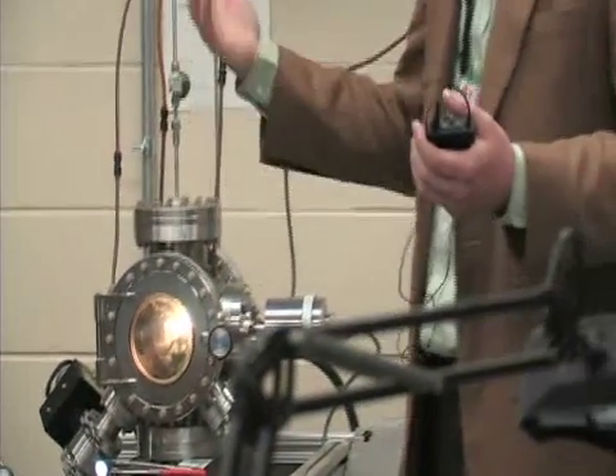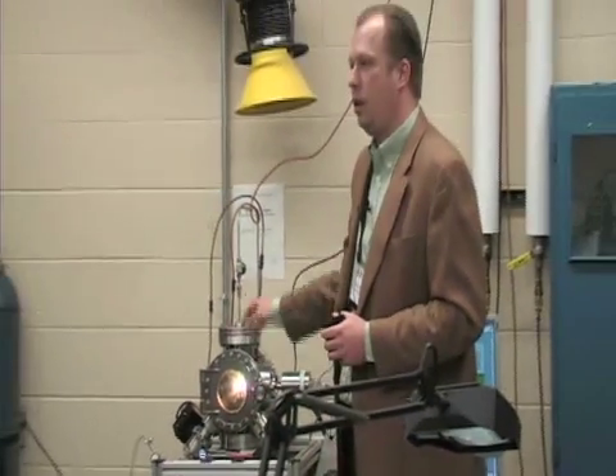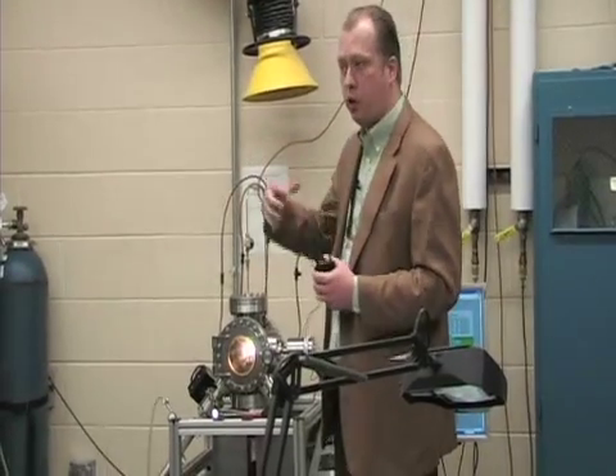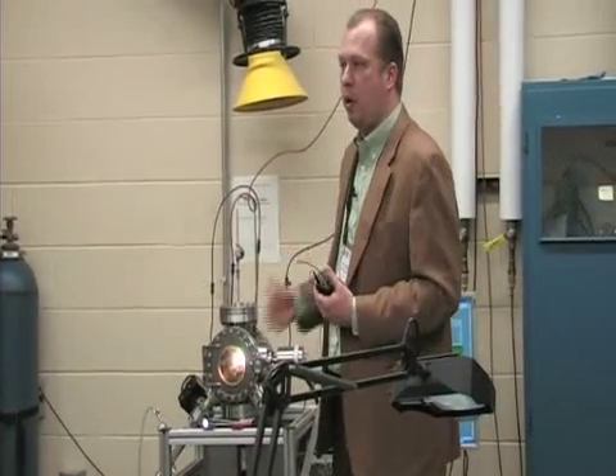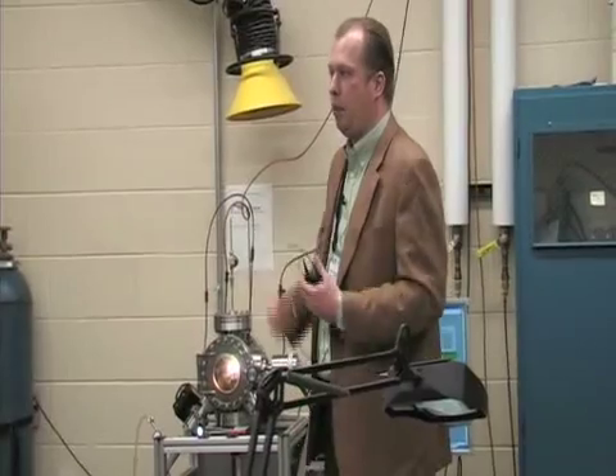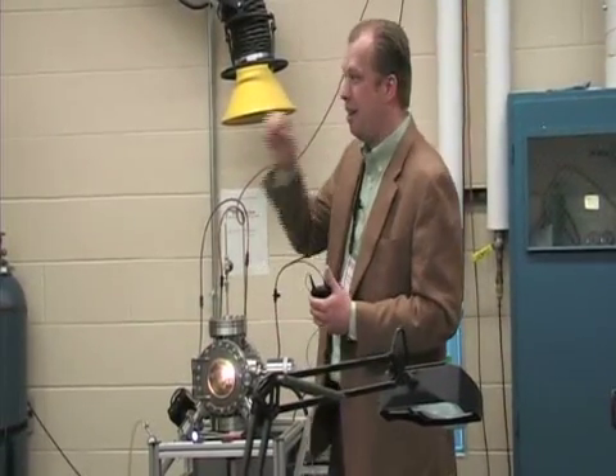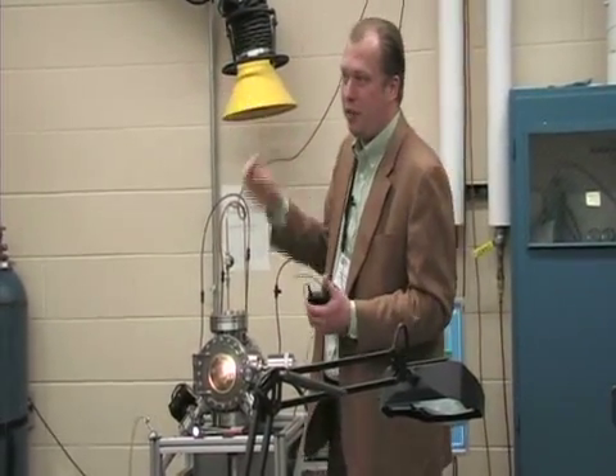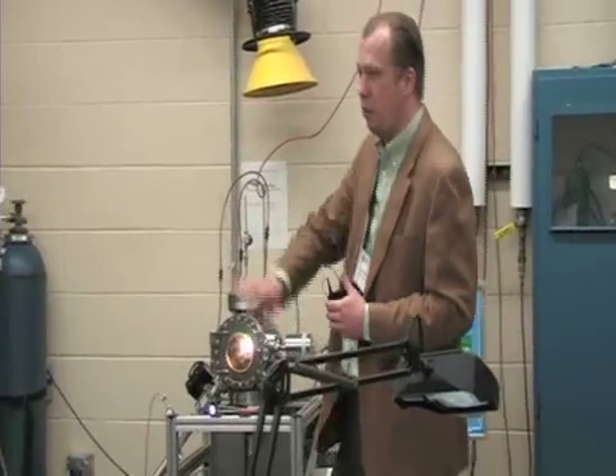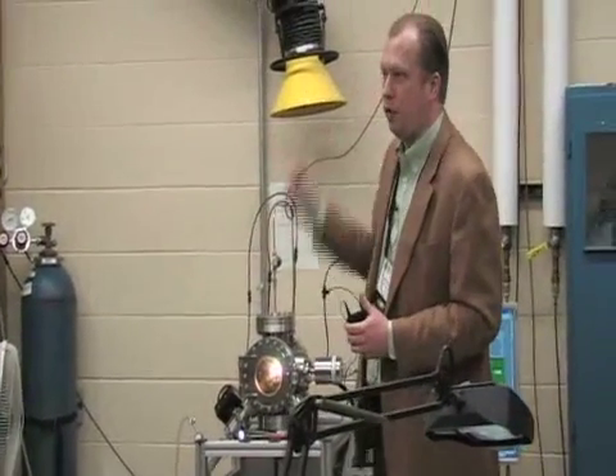Even with something as easily machinable otherwise as aluminum, we can see sometimes significant force reductions when we're micro end milling with the diamond coatings because there's less adhesion. And also, a big thing, the chips don't stick in the flutes. I'm not even just talking the cutting zone, but evacuating material up the flutes of the micro end mill.